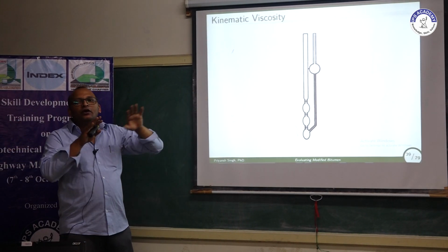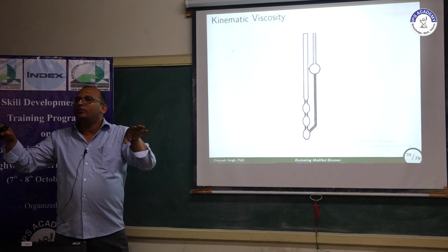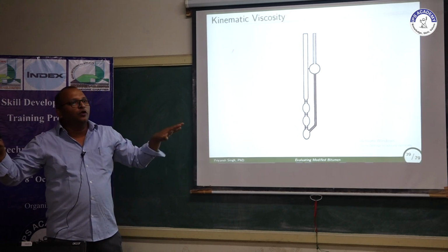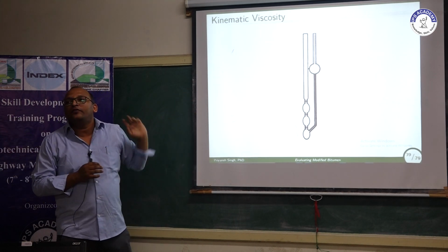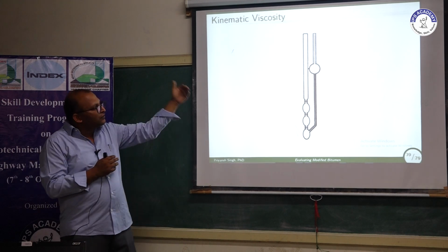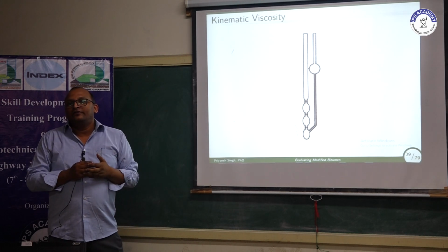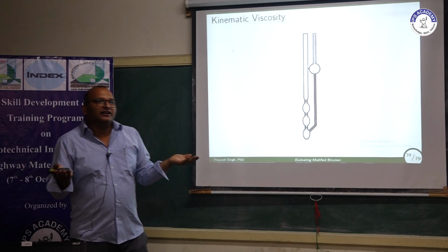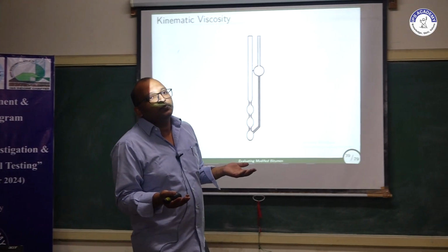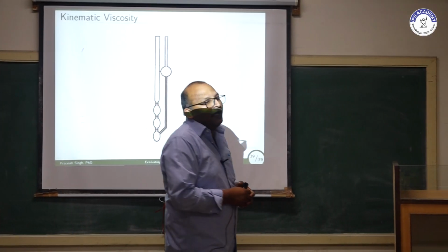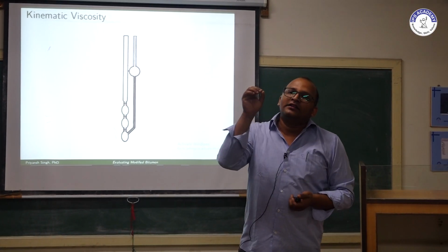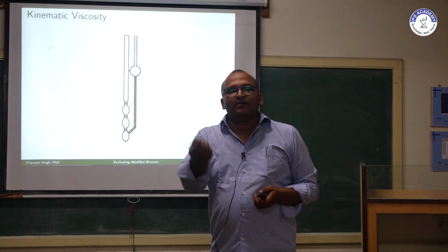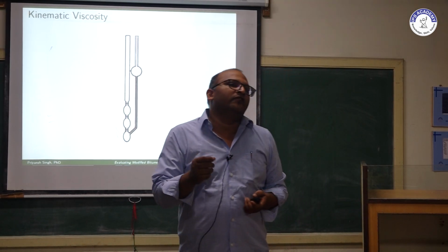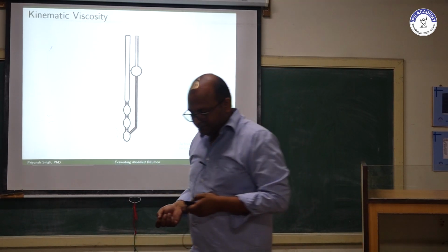But in this case we are not going to apply any vacuum or any external force in order to make our binder flow. The flow is occurring because of gravity, and this is the actual case which happens when you mix your binder with your aggregate. So that is why kinematic viscosity is the real measurement of how your binder will behave when you mix it with the aggregate.